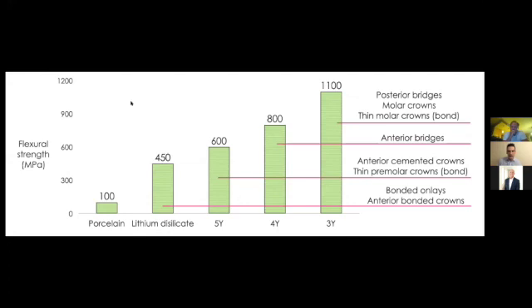For 5Y zirconia crowns, and this is again just my opinion, I think it's for people that aren't bonding, that are going to use RMGI cement. I think that 5Y is way safer than using lithium disilicate. So I think that's a great indication for the 5Y zirconias for anterior cemented crowns. Of course, you can bond them as well. And I guess this is where I get into that dummy-proof thing. Sometimes I've had issues trying to try in some thin premolar lithium disilicate crowns and have fracture during try-in. And so with 5Y, it just feels a little safer. You can try them in without having to worry about fracture. And once you bond them in there, they're going to be nice and strong.